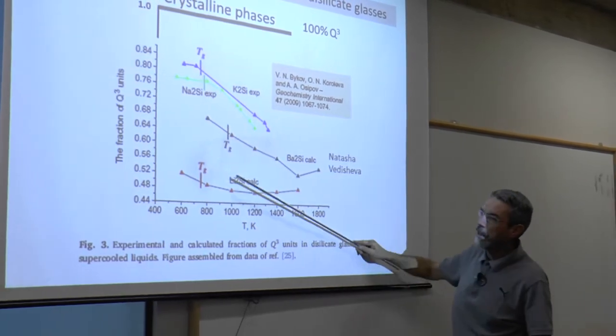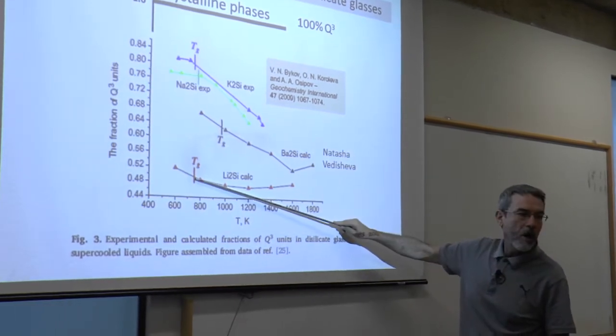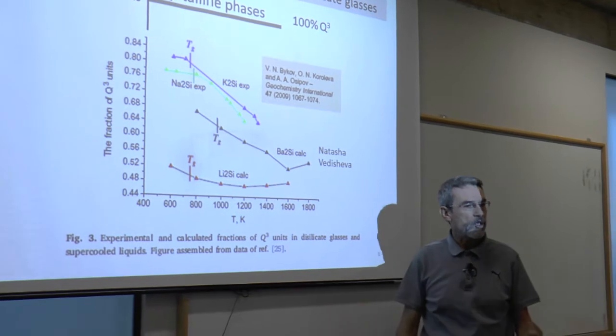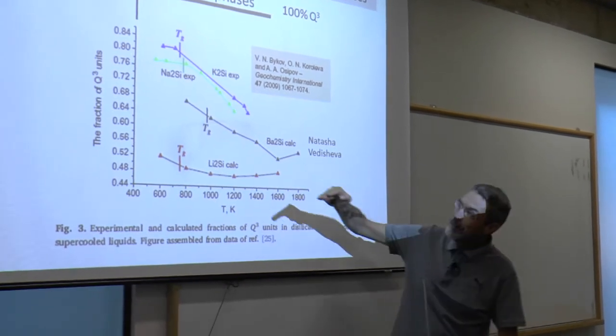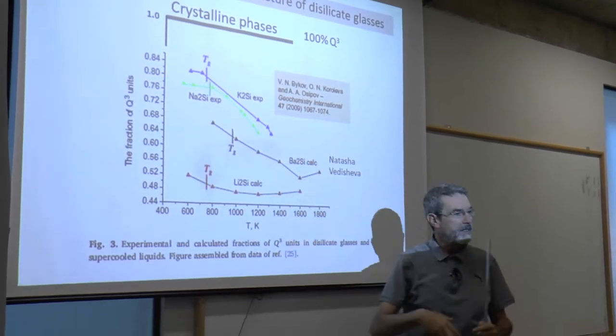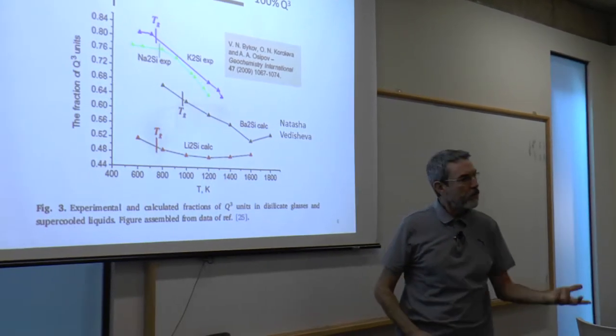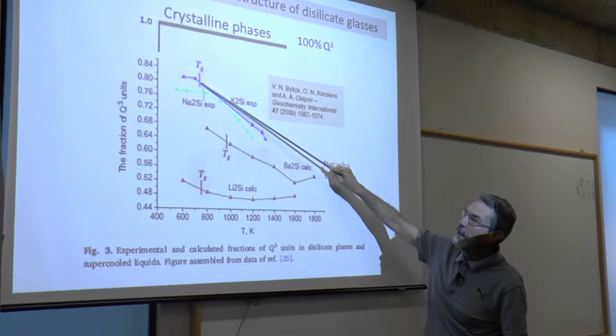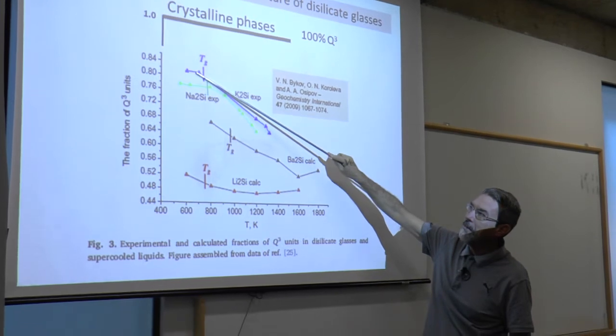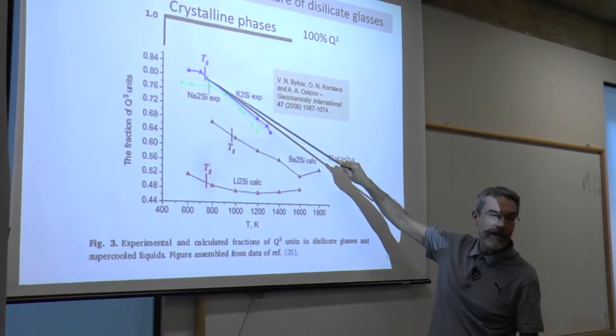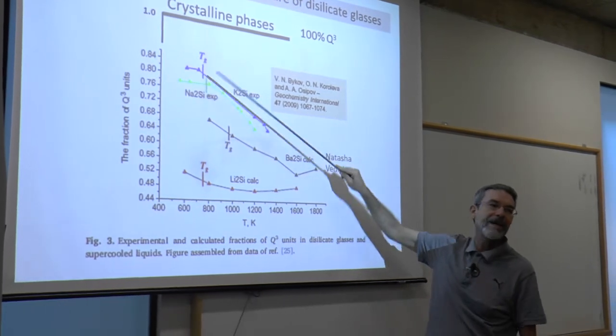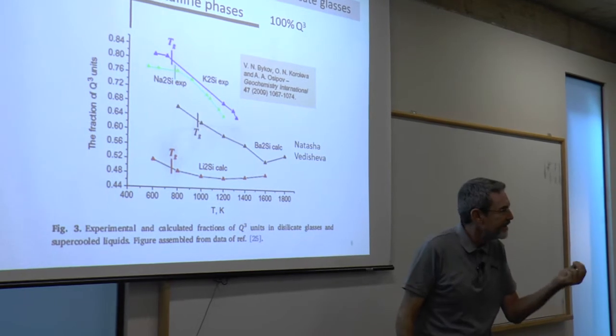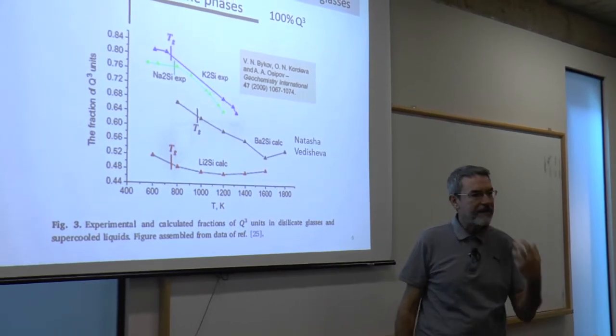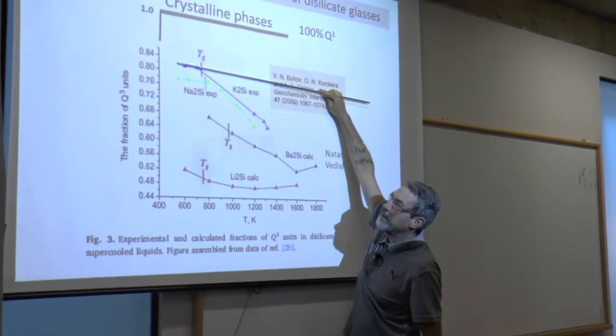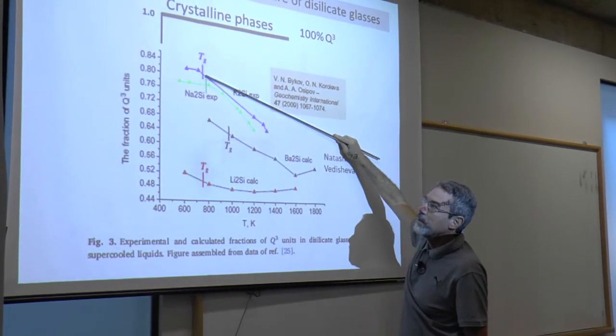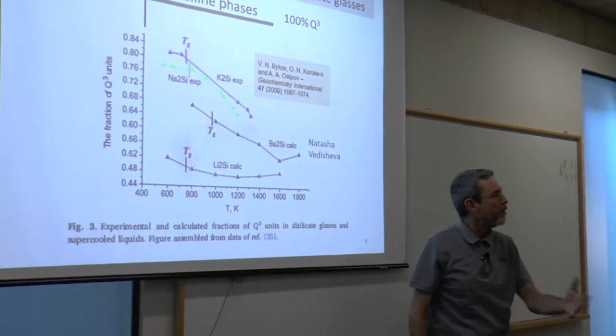For the lithium disilicate, 50% of the tetrahedra are sharing 3 corners. So this is a measure of how different the structure of these glasses can be, but most importantly, the structure of the glass below TG is about the same as the structure of the supercooled liquid. It has maybe 1% less or more Q3, but this is just the effect of temperature. The structure of the glass is the same as the structure of the supercooled liquid just a few degrees above TG.